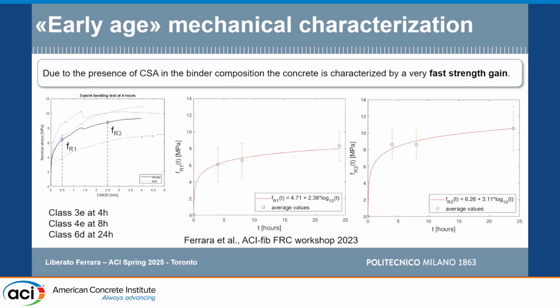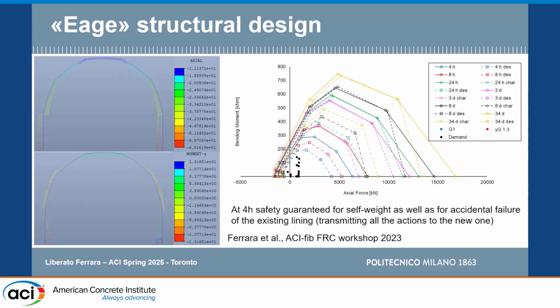So we did perform the test also at 4, 8 hours, and 24 hours, and you see at 4 hours, we had this average value with this scattering. You see how it increases. So the first step that we made was, okay, at 4 hours, which is the first age we were able to make the test according to the hardened state, and we can use conventional solid mechanics tools to analyze: is our tunnel lining safe? What does it mean safe? Well, first of all, it must self-stand. It must resist its own self-weight.